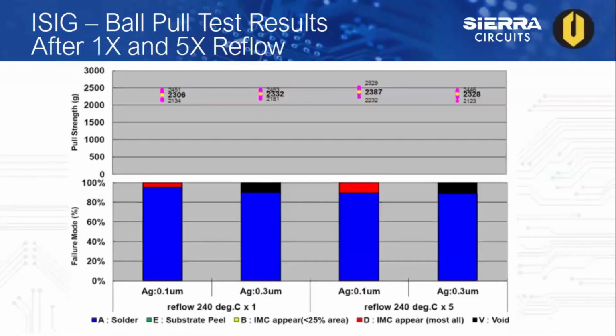Now here we have ball pull strength results for ISIG at 1 and 5x reflow at 240 degrees Celsius. The pull strength results are very similar. The failure modes did show some differences, and all the sample failure modes were mostly at the solder. However, both the 0.3 micron silver plated samples showed some voiding, while the 0.1 micron silver plated samples kept most of the IMC.